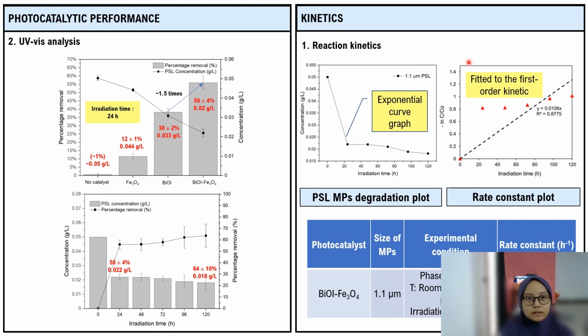Meanwhile, this figure shows the degradation plot of polystyrene microplastics, and it shows an exponential curve pattern. Hence, it is fitted to the first order kinetic, and it was observed that polystyrene can be degraded at the rate of 106 multiplied by 10⁻⁴ per hour.